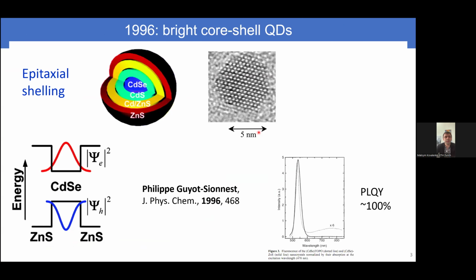In the meantime, in the mid-90s, core-shell nanocrystals were also developed. That's where the inorganic core was extended by an epitaxial shell, so that you keep the same crystal structure, but you keep growing a wider bandgap semiconductor so that you confine the electron and the hole to the core. And so they are no longer sensitive to all the dangling bonds at the surface, and you drastically increase the radiative rates. So you actually have very bright emission, which is approaching these days 100%.